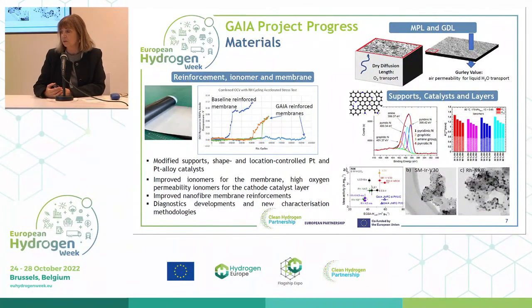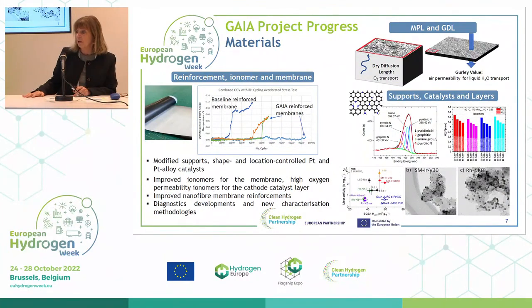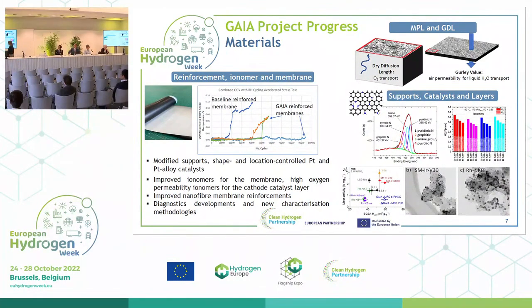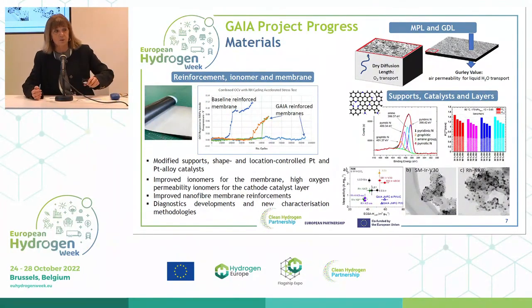With regard to the membrane, I mentioned that there were developments with respect to novel reinforcements, so moving away from, let's say, the conventional type of expanded PTFE reinforcement to reinforcements that are prepared by electrospinning, so nanofiber reinforcements, where we have a lot of control over the kind of materials that we use and their thickness and porosity. And those are some examples there in an accelerated stress test on the membrane once it's integrated into an MEA. This is the open circuit voltage and also with relative humidity cycling, showing the various generations of membrane and how we managed to increase that durability over the number of cycles during the course of the project to something that in the end was just an end of test, so it was a virtually indestructible membrane.